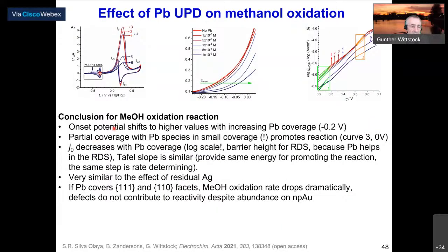Okay, so the conclusion is that the onset potential shifts to higher values with increasing lead coverage. Partial coverage of lead, with small coverages but only with small coverages, promotes the reaction. The exchange current density decreases, but that decrease maybe looks small, though it's a logarithmic scale. And the Tafel slopes are similar, so we assume the same step is the rate determining step. This is similar to the trends we observe for residual silver. And if lead covers these low index facets, then the methanol rate drops dramatically. So that's this change from here to here.